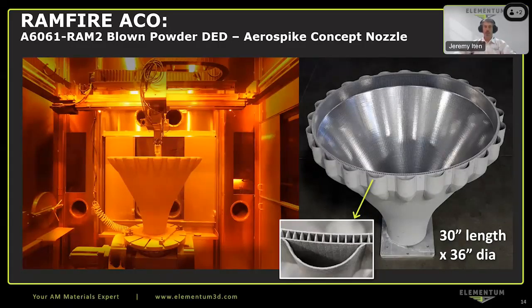So again, on the left, you can see now the RPM Innovations blown powder DED system producing, in this case, the aerospike concept nozzle. It's a very large concept part, thin-walled with regenerative cooling channels throughout. And then on this image on the right, you can see the shiny interior surface that was finished with REM surface engineering using their REMChem type process to surface finish that part to a polished, almost a mirror type finish. This is a 36-inch diameter part, so again, quite large.